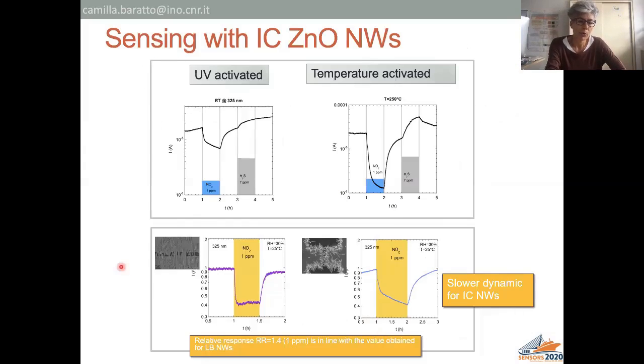Going to sensing properties, we were able to compare the Langmuir-Blodgett aligned nanowires with the intercrossed nanowires, and the relative response was nearly the same, but the response and recovery times were higher. Here, the time waited in gas was 1 hour, while here it was half an hour. And so we have a slower dynamic for the intercrossed nanowires.